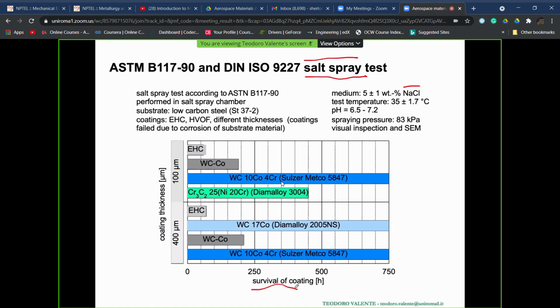And if we have a look here at the figures given by this salt spray test procedure, in terms of survival of coatings or hours inside the chamber where the salt is sprayed, well, this is the hard chromium. This is the standard tungsten carbide cobalt made by HVOF. This is a nickel chromium carbide made by HVOF, and this is the solution of HVOF spraying tungsten carbide, cobalt, and chromium.